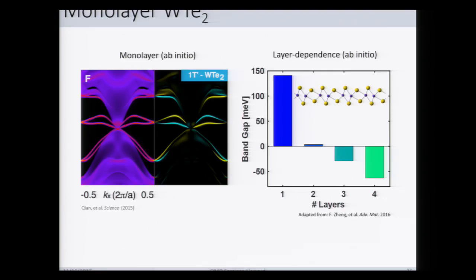What I didn't mention before is that the initial calculations showed that, okay, here's your valence band. This is energy and momentum. Here's your conduction band. They're actually not quite touching here. They're actually overlapping in different parts of momentum space. This would mean that you actually have a semi-metallic state, just like what I described to you in the tri-layer and for the 3D samples.